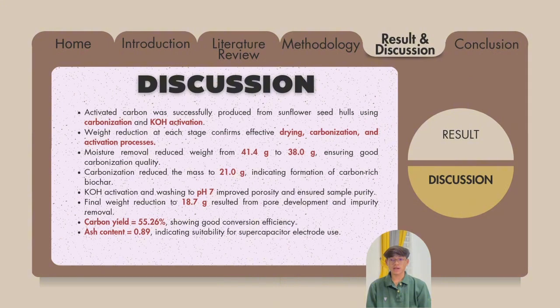For the discussion, activated carbon was successfully produced from sunflower seed hull using carbonization and KOH activation. Weight reduction at each stage confirms effective drying, carbonization, and activation process. Moisture removal reduced weight from 41.4 gram to 38 gram, ensuring good carbonization quality. Carbonization reduced the mass to 21 gram, indicating formation of carbon-rich biochar. KOH activation and washing to pH 7 improve porosity and ensure the sample purity. Final weight reduction to 18.7 gram resulted from pore development and impurity removal. The carbon yield 55.26%, showing good conversion efficiency, and the ash content 0.89, indicating it is suitable for supercapacitor electrode use.